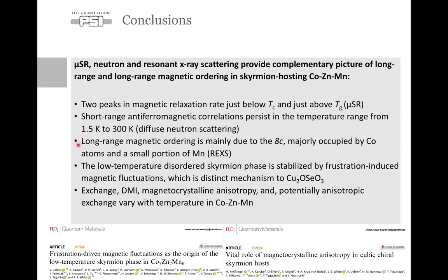And also, we identified that the long-range magnetic ordering is mainly maintained by cobalt ions at 8C site, while manganese at 12D site is mainly frustrated and does not participate in helimagnetic ordering, but rather in short-range correlations. Also, we have proved that the low temperature disordered Skyrmion phase in cobalt zinc manganese 736 is stabilized by slow magnetic fluctuations rather than by magnetic anisotropy, which is the main mechanism for disordered Skyrmions at low temperature in copper selenide. And also for cobalt zinc manganese 884, we have shown that the exchange interaction, DMI, magnetocrystalline anisotropy, and potentially anisotropic exchange vary with the temperature. And this is probably the case in other materials in this cobalt zinc manganese family, which makes the story even more complicated. Please take a look at these two papers to get further details.